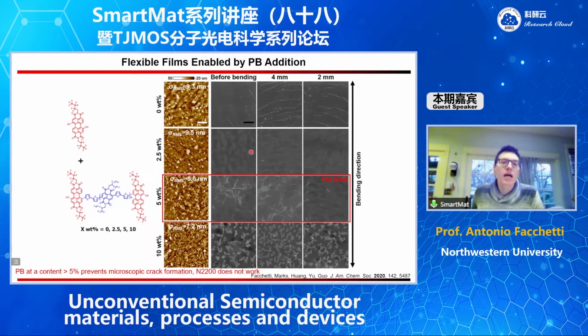So what we did, to prove the concept, is prepare films with the small molecule, adding this polymer in different content, going from 0, so only the small molecule, to 2.5, 5, and 10%. And then we started bending this film.